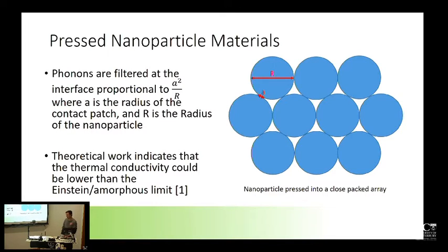I think one of the things that aerogel has over a packed structure is that it's also very mechanically sound and it's quite light for volume. So while this might be able to beat an aerogel in pure thermal insulation performance, it's also 100 times as dense as an aerogel. So while you might be getting, say, 6 milliwatts per meter Kelvin from this and 20 milliwatts per meter Kelvin from an aerogel, you're still getting 10 times the weight for the same thickness of material. But yeah, they do actually use these types of aerogel type materials in most satellites to keep them warm.